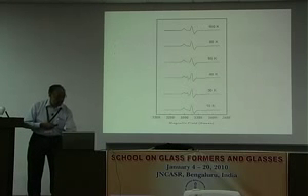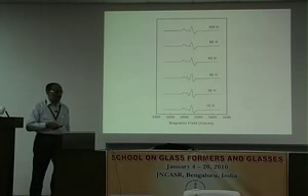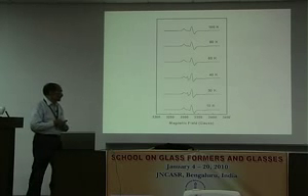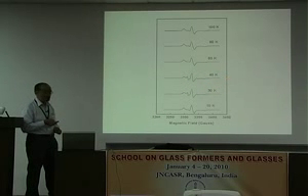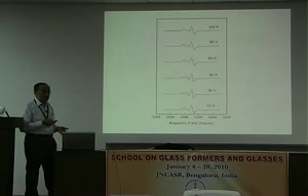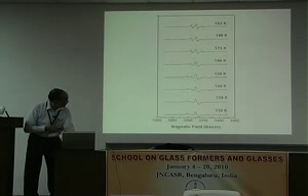So, that brings me to the present work. This sample is again of water, but in a slightly different matrix. Here again it is quenched to liquid helium temperatures to see amorphous water, but when it is warmed up, you begin to see the signals of liquid water even at much lower temperatures, at 30 K, 40 K and so on, compared to the glass transition temperature of 135 Kelvin roughly. So, this is the new result we have got.